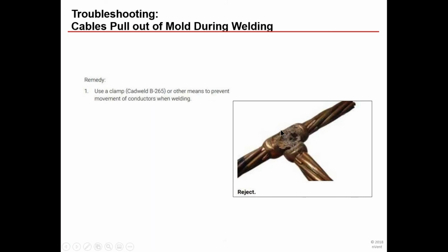Here's a situation where, as you can see in the middle, it's pitted and looks like it's sunk in the middle. This is an indication that your conductor separated, and all that weld material, instead of going around your conductors, went around here and here, but settled into a big block in the middle. This is something you have to look for. If you do experience this, it is recommended that you reject it and start over.